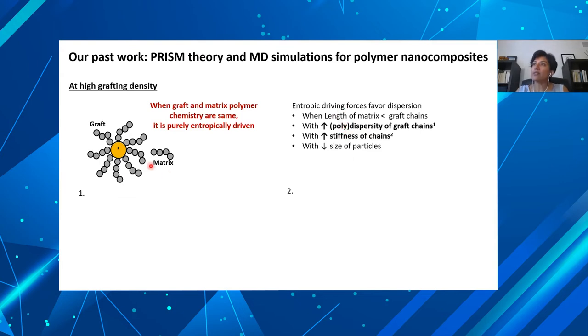But what we found is, when the chemistries are the same in the graft and the matrix and you have high grafting density, the way to tune those entropic driving forces to favor dispersion is by choosing molecular weights such that the graft is a really large molecular weight and matrix is small. So then the mixing entropy of the matrix penetrating the graft layer is dominant, and the conformational entropy loss of the matrix upon entering the grafted layer is small. So it basically wants the two to mix, particles and matrix mix, you get dispersion.